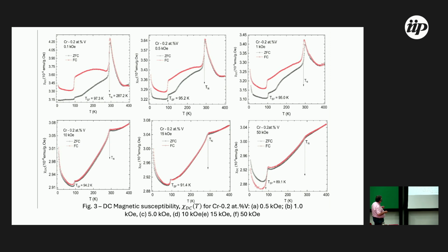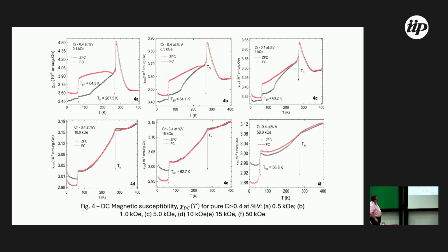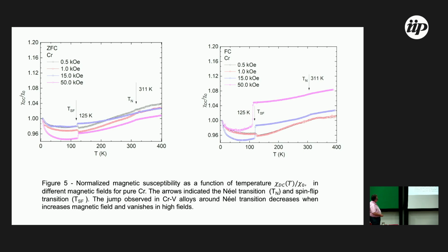And in the case of the sample with an increase to 10 kOe, the reversible behavior disappears. And the same in 0.4%, this ferromagnetic behavior is more clear when cooling down the sample. And we observe the effect of this jump compared with this jump. I show all samples in the same fields. It is easier to observe. And the zero field cooling and field cooling of chromium, in particular, when increasing magnetic fields, the change of the spin flip jump here. Okay?